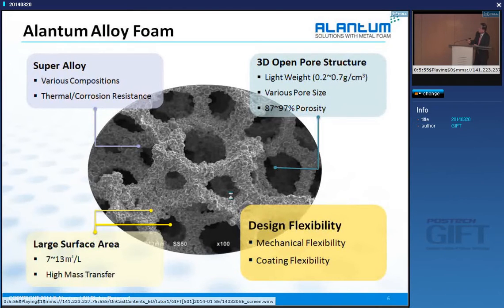Because of this porosity, we have a very light weight, with over 90% porosity. And then we have a dramatically larger surface area, roughly 7 to 13 square meters per liter. If you compare with conventional ceramic material, that could be about 3 or 4 times more, okay? And definitely we have high thermal and mass transfer. And then I can also show you that we have design flexibility, mechanical flexibility, as well as coating flexibility.